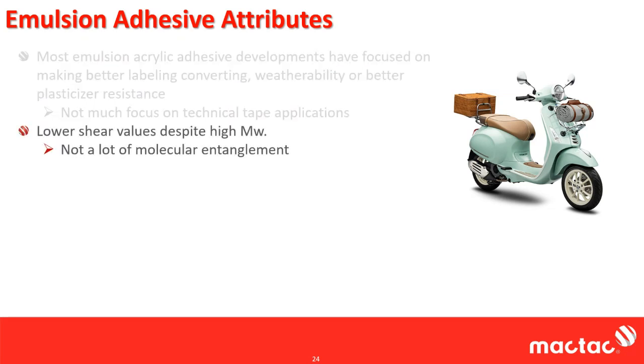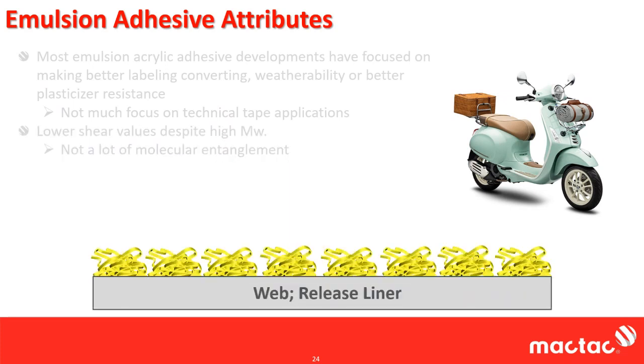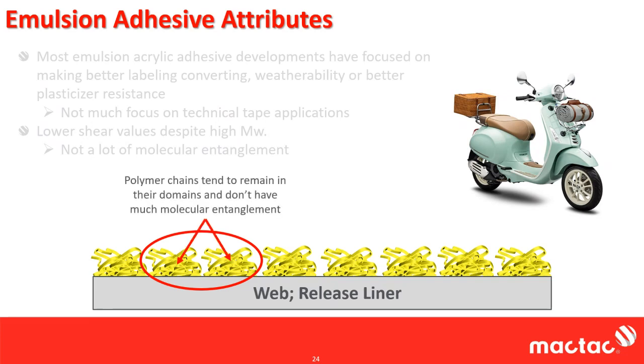A lot of what I talk about is driven by molecular weight. Well, emulsions are really high molecular weight. In fact, a lot of people that know adhesives and polymers are surprised to find out that of the adhesives, emulsions have the highest molecular weight. But the problem is that you don't get a lot of molecular entanglement. If you go back to that web with the dried polymer, I showed it as being homogeneous. In reality, though, you get more like defined domains. Since when you're doing this polymerization, you're doing it in that micelle, and everything's clumped together, you might get a lot of high molecular weight, but you don't get very much molecular entanglement.